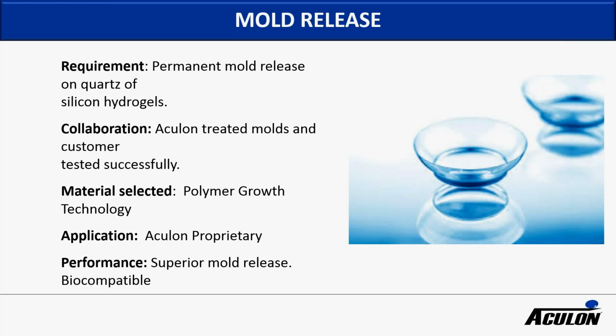Another area that's been interesting is mold release. We've actually used both hydrophobic and hydrophilic treatments for mold release. In the case of silicone hydrogels, we found the hydrophilic treatment to be especially effective. The customer sent their molds in, we applied a SAM and grew a polymer and returned them, and have gotten really good results in terms of mold release. Furthermore, there's been some biocompatibility testing done on the treatments, and as we know, our treatments are non-toxic, but in this case there was quite extensive testing done and found that the treatments were completely biocompatible for FDA compliance.